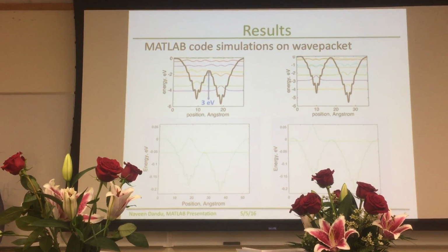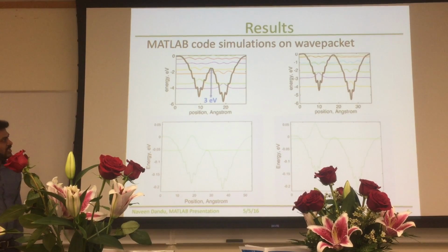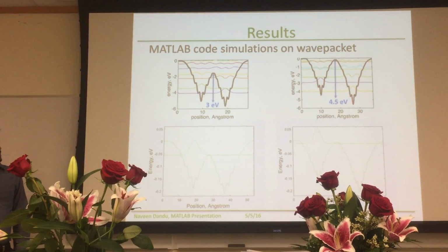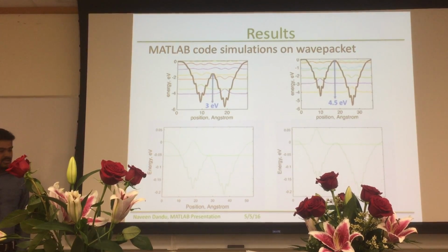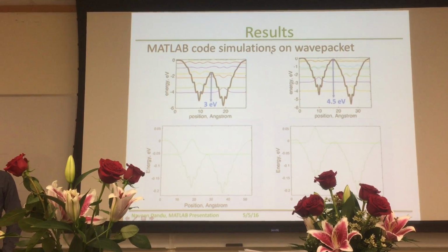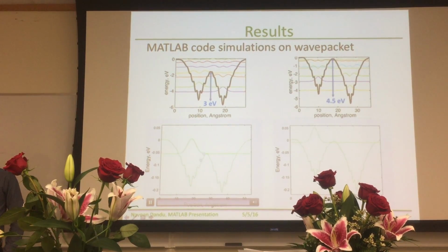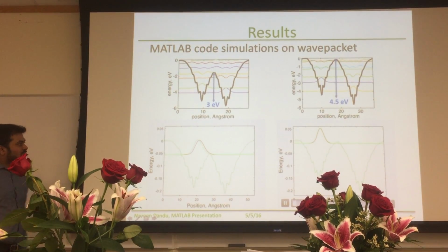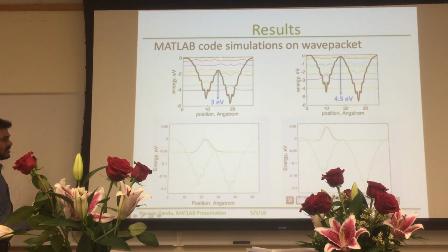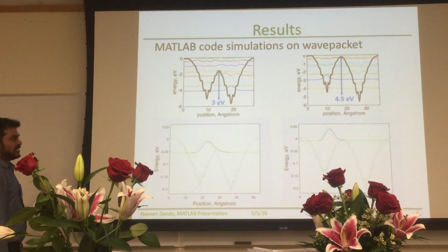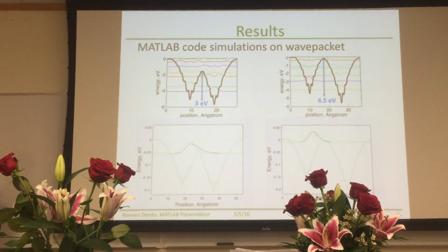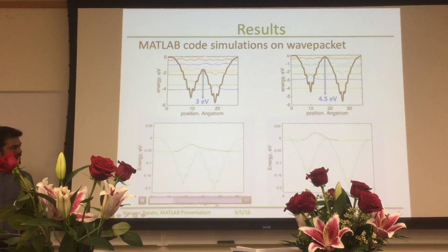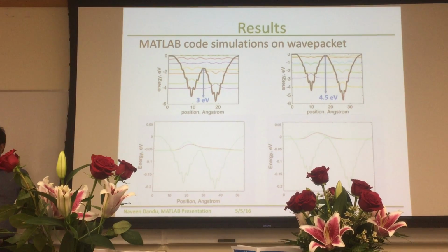As you can see, the activation barrier for bridged dimers is much less, like 3 electron volts, compared to the activation barrier for disconnected dimers. And I also have these movies of the electron transfer dissipation from one quantum dot to another in the case of bridged dimers versus the disconnected dimers. As you can see, the electron dissipation is much faster, or much more contributed towards the right quantum dot, in the case of bridged dimers versus the disconnected dimers.